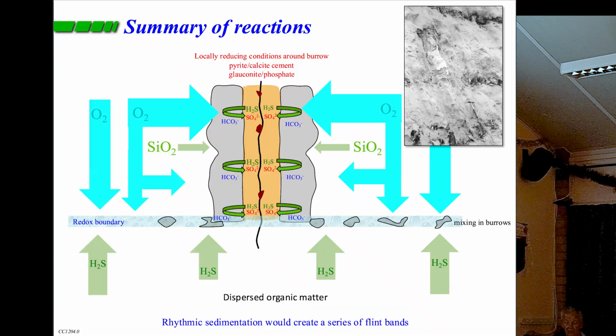So essentially we've got our central burrow in there. We've got oxygenated sediments all around it. We have sulfide moving out, being oxidized to sulfate, and then migrating back in again. And we have silica all around us, and that will precipitate where the carbonate is dissolving.